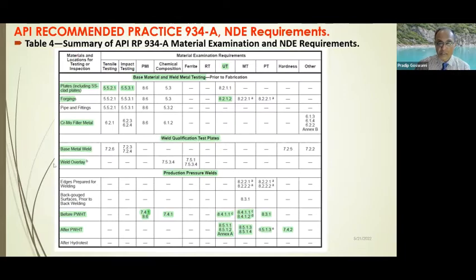Weld qualification test plates, you need the tensile, and you need hardness and others. Basically, you have to have the step cooling requirements. And weld overlay, you require chemical composition, ferrite, and other NDE tests as mandated by the project specification. And production welds, you see here, weld edge preparation, you need MT or PT. And for the back gouge surface, you definitely need MT. Before post-weld heat treatment, you need PMI, chemical, UT, MT, PT, as well as after post-weld heat treatment, all these three steps, that is UT, MT, PT, and hardness. These tests have to be performed.